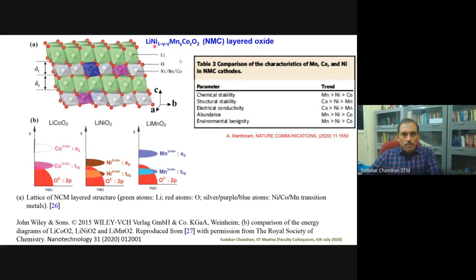So this particular compound is very special for the reason that in presence of manganese, nickel always tries to stay in the 2 plus state because of the energy levels. So it reduces the nickel, manganese gets oxidized, and therefore the chemical stability for manganese is much better than this. And most of the lithium redox happens between the nickel and cobalt compound. And this particular one gave much better capacity, up to 160 milliampere hour per gram.